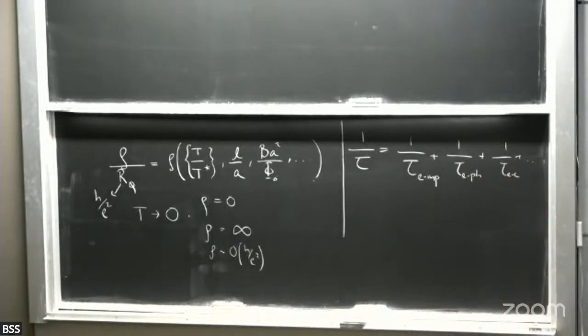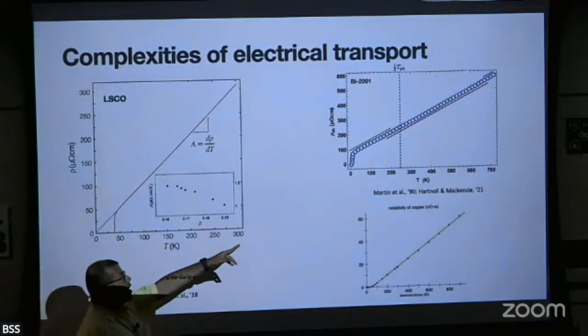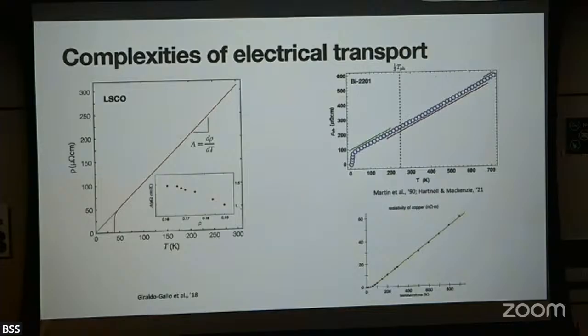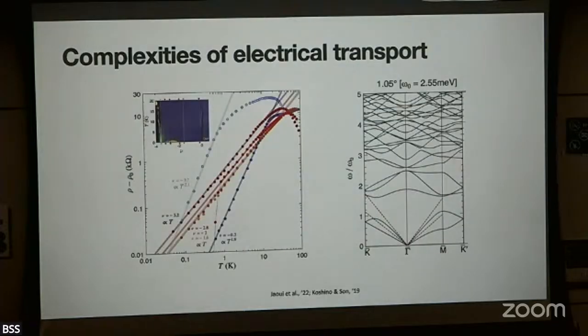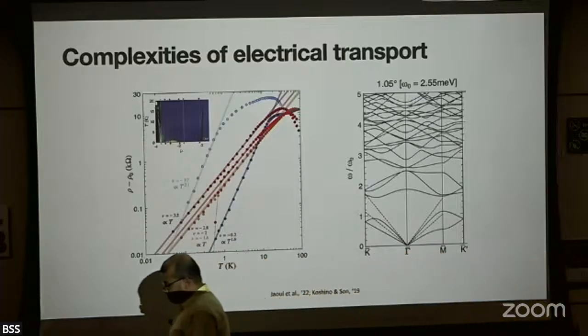For instance, what this particular data is trying to show is the red region is a regime where you might be able to explain the T-linear resistivity as being due to a particular phonon mode, but there's no way you can explain what the green part of the resistivity is coming from. And similarly, if you just keep going to higher and higher temperatures, there will be similar onset of other phonon modes. So how do you explain this relatively large range of temperature scales, which have just a single slope, so to speak? The other example, which is more recent, arises in twisted bilayer graphene, which you heard about last week.